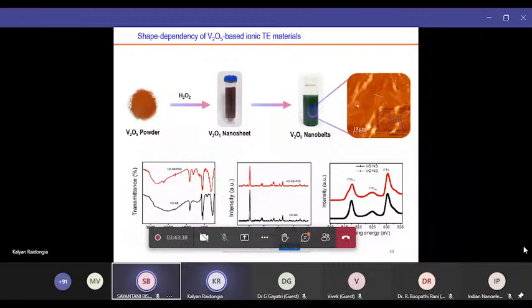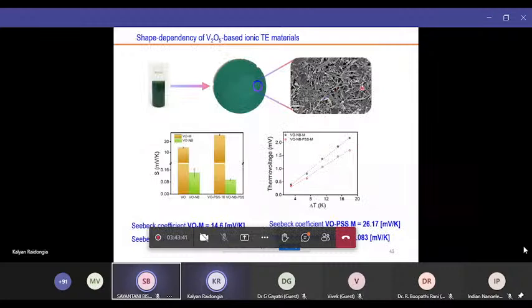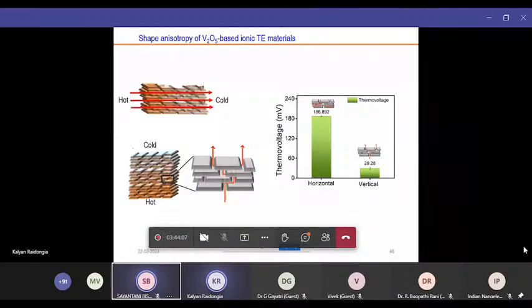Now, if we prepare a device with this unorganized vanadium pentoxide material, we don't see any good effect. It was initially 14.6 for pure V2O5. With nanobelt, it is just 0.094. Similarly, with PSS, it was giving us 26.17, but with the nanobelts, we got only 0.083. So this 2D layered structure is very important for this application. Same thing when we measure the voltage in the horizontal direction, where ions can easily move from one side to another, we get a very good voltage. But when we measure from top to bottom through this zigzag way, where it is very difficult for ions to move in this direction, we get a very small thermal voltage.